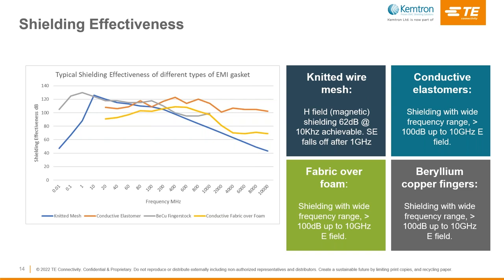Conductive gaskets can offer shielding effectiveness of up to 120 dB; however, this is under perfect testing conditions. High contact resistance between the gasket and enclosure can degrade or negate any shielding effectiveness. High resistive passivation finishes or oxides on the gasket mating surfaces will cause the gasket to fail, as there will be little or no conductive path between the gasket and the mating surface. This is particularly a problem with smooth surface gaskets such as conductive fabric over foam, as only small amounts of pressure can be applied. Aggressive rough-finish gaskets such as wire mesh will penetrate the resistive finish, but may not be suitable for every application. It is therefore important to pay attention to mating surface cleanliness and ensure the surface has a good conductive finish.